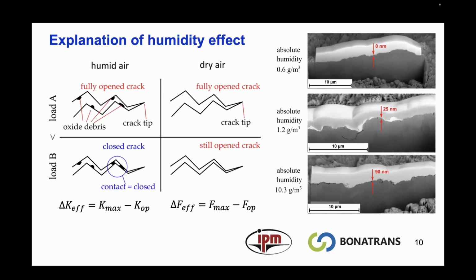We have observed this fact in electron microscopy. There was no evidence of oxide in dry air, and quite an important 90 nanometers of oxide in normal humid air.